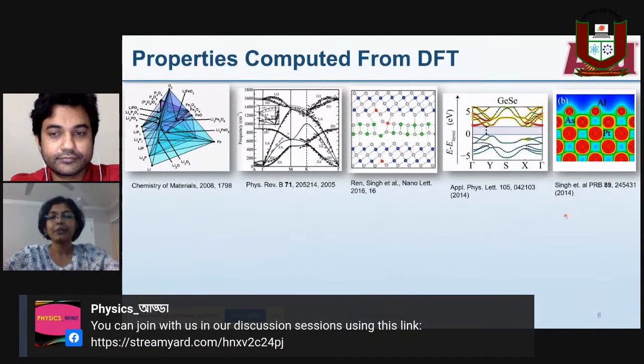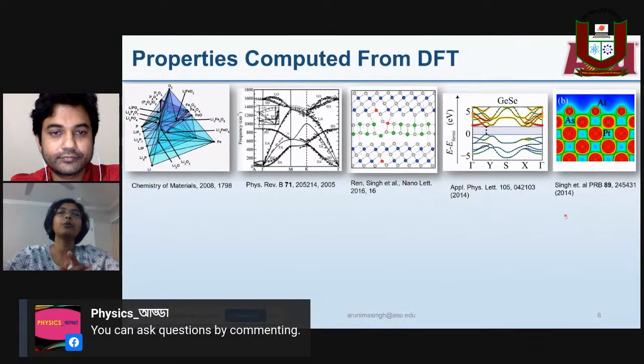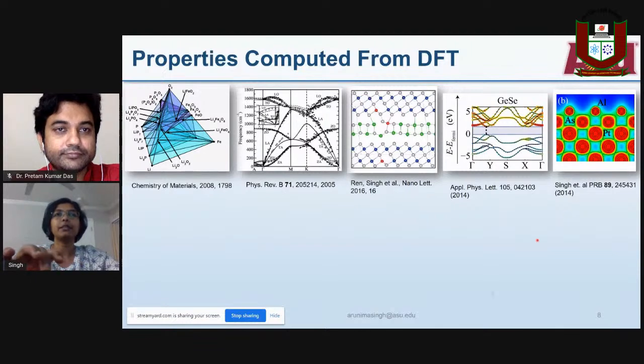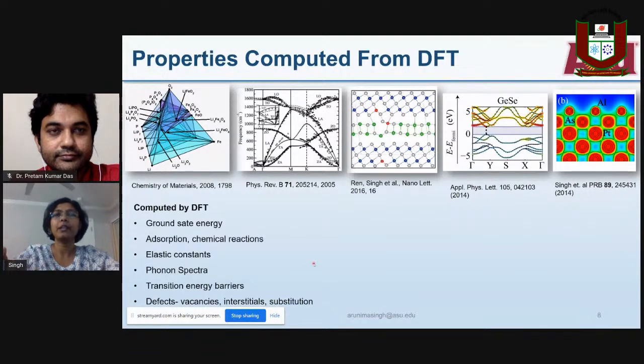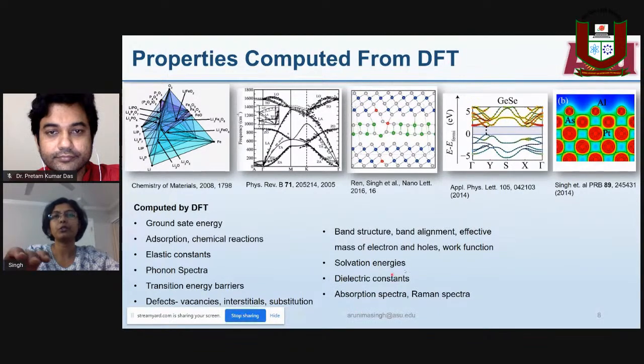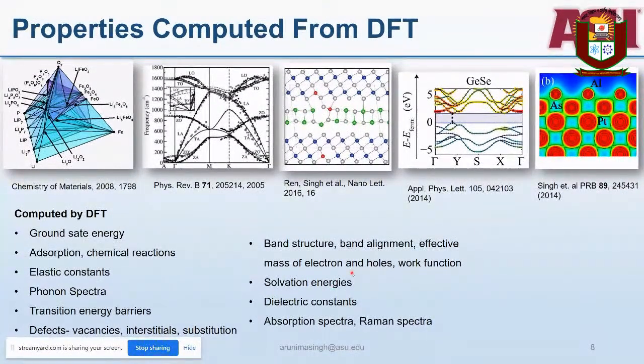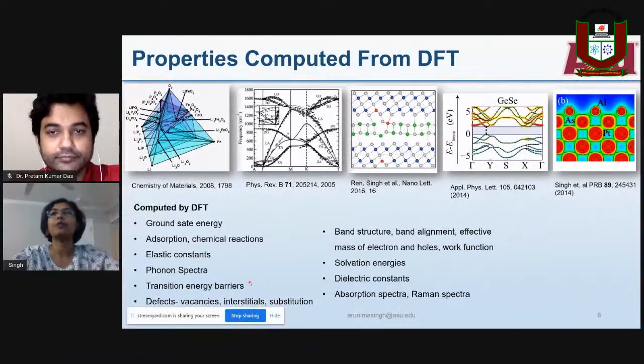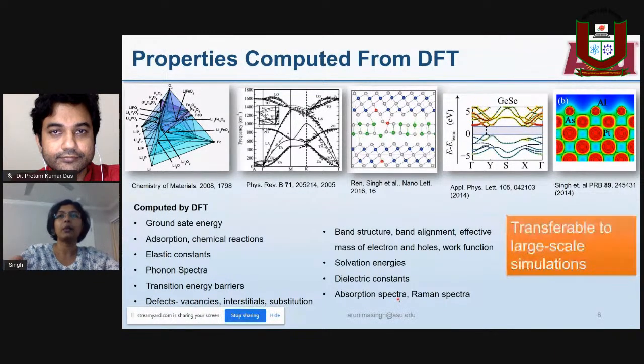The properties which are computed from DFT, as you know, it's a ground state theory, range from looking at the phase stability, the phonon spectrum, and the defect distribution in materials, to the band structures or the charge densities. In fact, there are many, many other properties which can be computed from density functional theory. I won't go into the details, but I want to mention that there are some which can be predicted with reasonable accuracy, perhaps within 5% of the experimental measurements, while others are much more inaccurate, and there are higher order methods which can be employed.